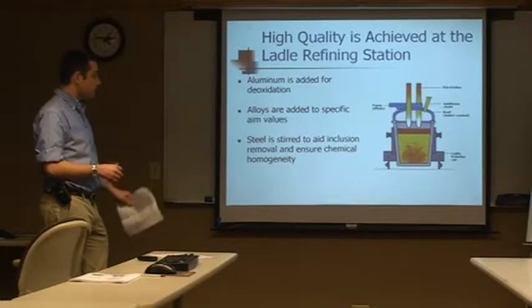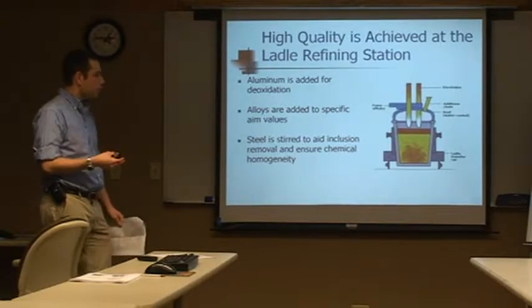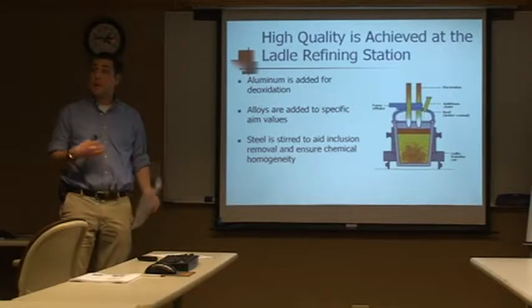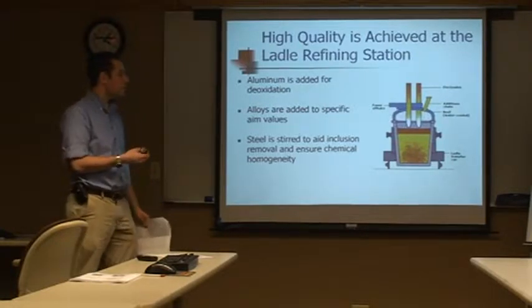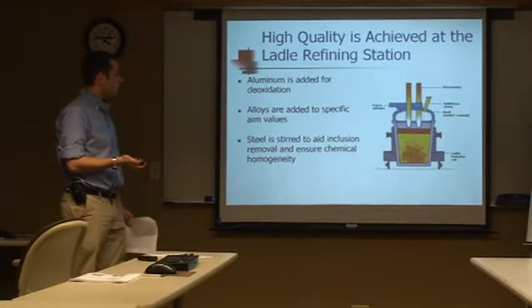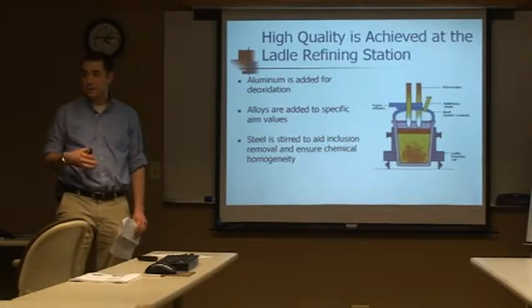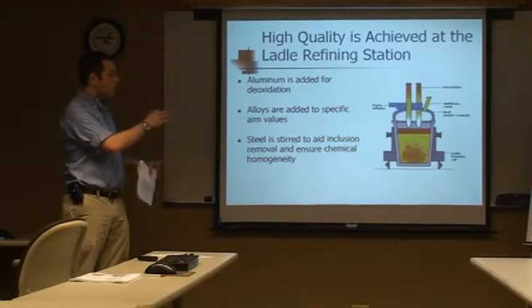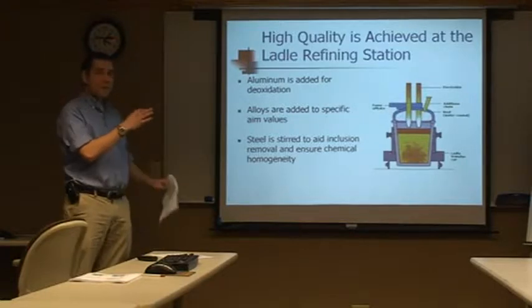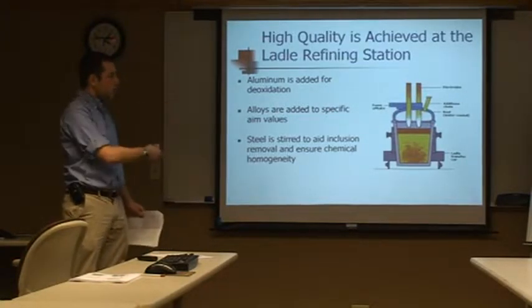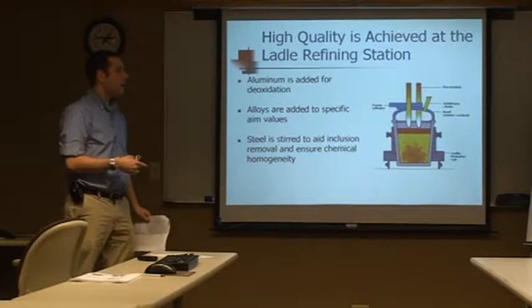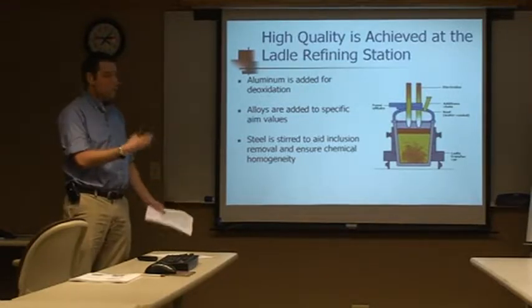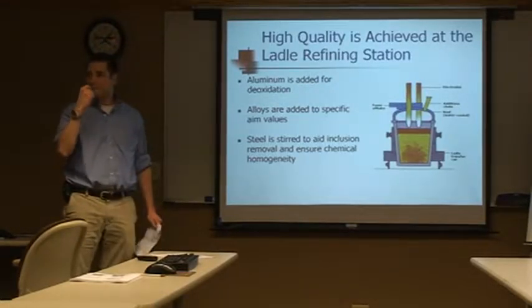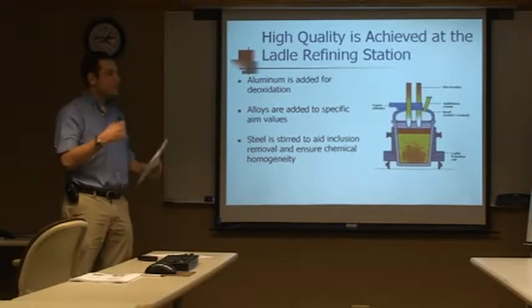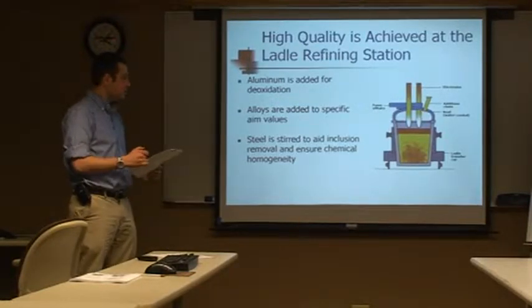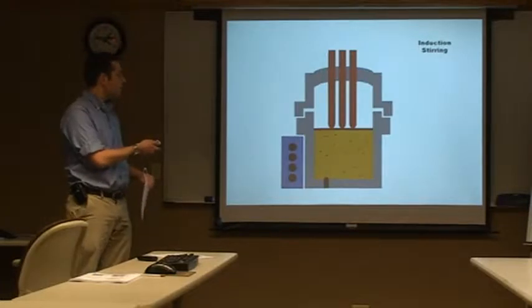In addition, to help keep the temperature uniform and also to help keep the chemistry uniform when we do add in some alloys, we'll utilize a process called induction stirring. And induction stirring, remember from the video, we use magnetic forces to turn the steel over and roll it around in the ladle. It's basically mixing the steel without putting in something mechanical to stir it around, using magnetic forces to stir it. And we have an animation of this as well.